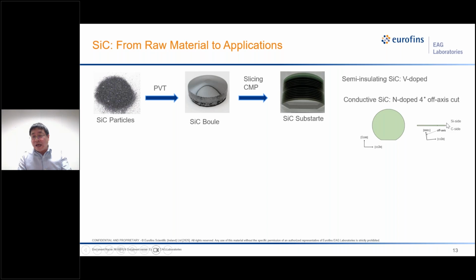I want to add one more comment: for the silicon side, it has a better, wide range of control of nitrogen. So this is very important for the epi growth. And also a 4-degree offcut is necessary for the CVD, for the epitaxial process, because it will provide the nucleation site for the epitaxial growth.